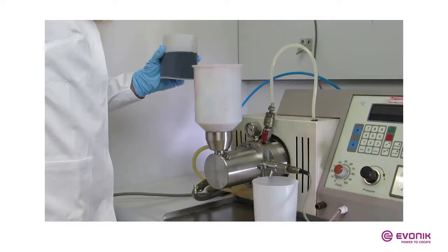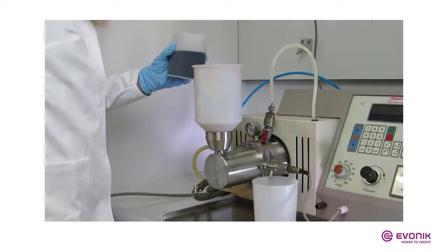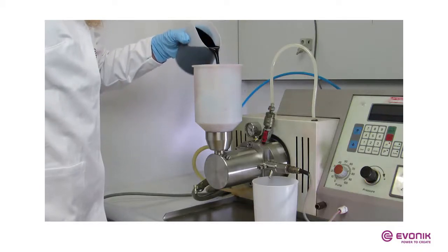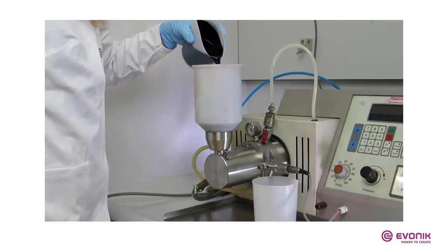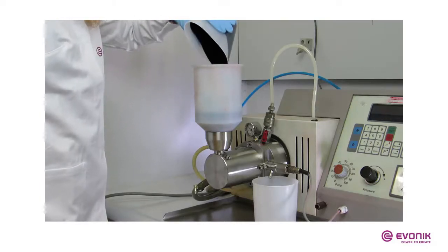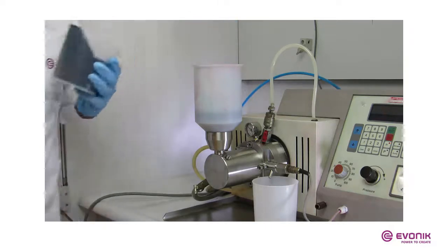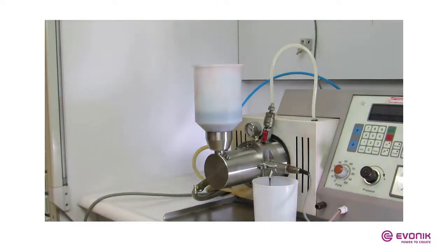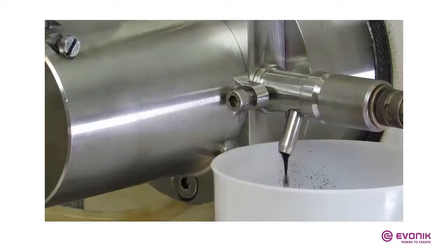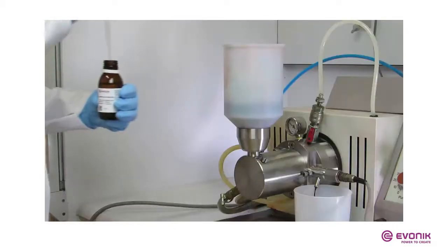Okay, so in this short video now you can see the effect of a grind aid. So what we did is we made a premix with carbon black and 755W in this case. And then we try to grind this in a bead mill. So when we put it into the bead mill, now we start the grinding. And what we can see, the bead mill is running, but it is not really smoothly. So you can see it's just going droplet by droplet.